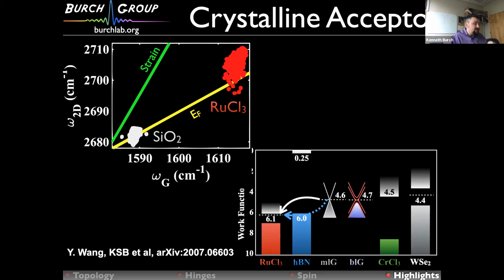And so what you see here in the white dots is where the graphene was sitting on top of just silicon oxide, and we see basically no strain and a little doping. And then when the same graphene is sitting on top of the ruthenium chloride, we see an enormous shift along the doping axis. That's equivalent to roughly a 600 meV shift in the Fermi level of the graphene.